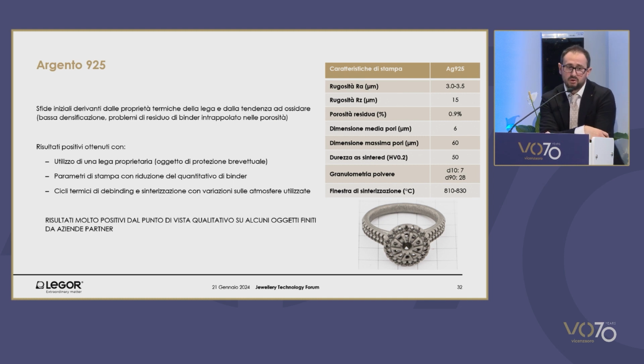Silver has been the first precious material we have worked on. So we started on the metal, because we're starting with sterling silver at the beginning, but the eutectic phase, which is marked in the binary alloy, represented a problem for densification. So this is why we changed the formulation to minimize the problem. And final residual porosity now is less than 1%.